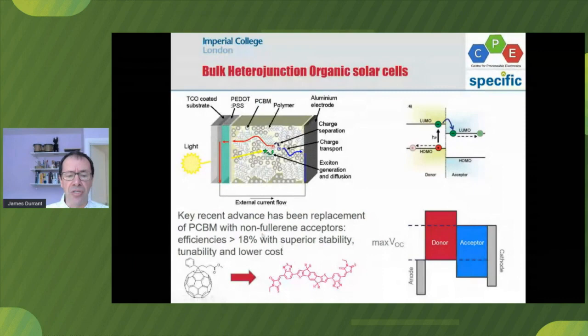You'll see one example of those non-fullerene acceptors at the bottom there: IDTBR. This switch from PCBM to non-fullerene acceptors, NFAs as they're often called, has now led to efficiencies for single junction cells which, while still lower than perovskites, are 18% and carrying on going up. At the same time, these non-fullerene acceptors show some advantage of stability.